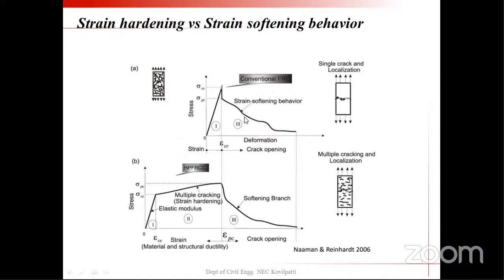So in the first diagram, you can see three parts. First it is moving in an ascending manner and reaches the peak stress. For this type of conventional FRC, you can see only one crack has been formed, and that one crack is called single crack localization. This crack will open, and it will not take any stress. Normally you can see the stress is also lower than the peak stress. After that, the fiber bridging across that one crack will fail by either pull out or by rupture, and concrete will offer some resistance, but it is very negligible. So after this crack localization, it will not take any stress. It is decreasing and finally reaching a negligible value.